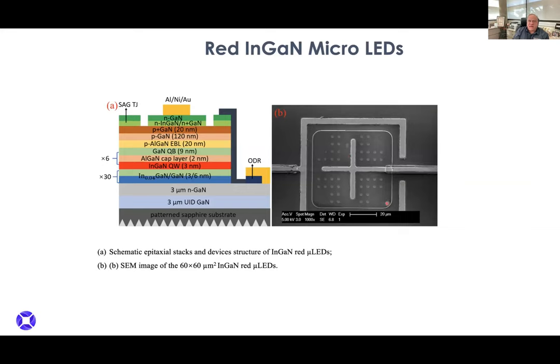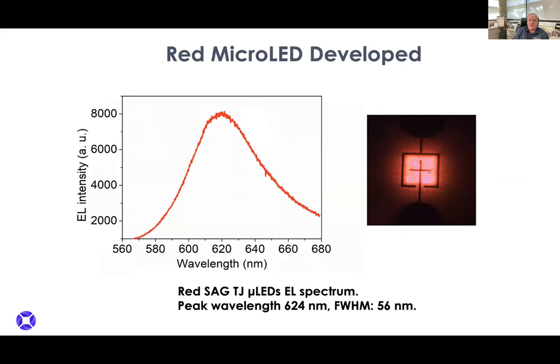You can also see this is a 60 by 60 micro LED. We put in the little holes here, developed by Dr. Abdullah Hassan, to get the activation up. So that is now, let's just put this N-type gallium nitride directly on the P-type. And this gives you a nice bright red light. So this is true red micro LED at 624 nanometers. A little broad, but it's still good enough because they can just put a filter on it to make it as narrow as you want.